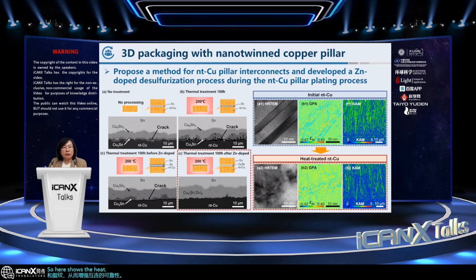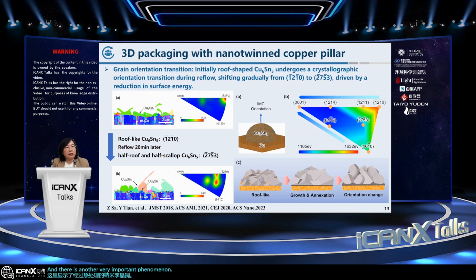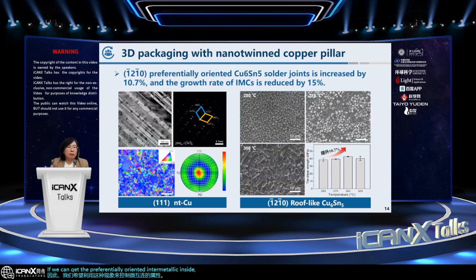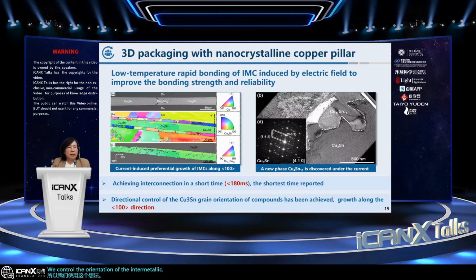So here shows the heat-treated nano-twinned copper pillar. And there is another very important phenomenon: if we reflow the nano-twinned copper pillar, a grain orientation transition will occur. So we want to use this phenomenon to control the properties of the micro interconnection. If we can get preferentially oriented intermetallics inside the copper pillar, the strength will increase, and we can also control the growth rate of the brittle intermetallics. So we use this idea. We control the grain orientation of the intermetallics by the electric field to improve the bonding strength and the reliability.